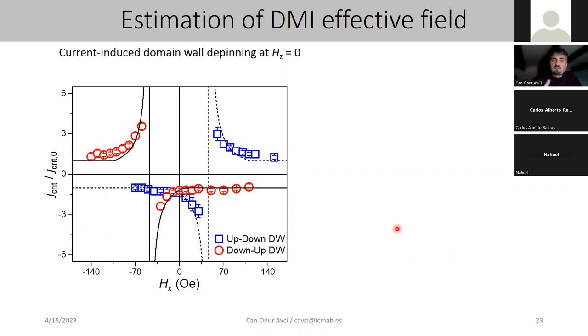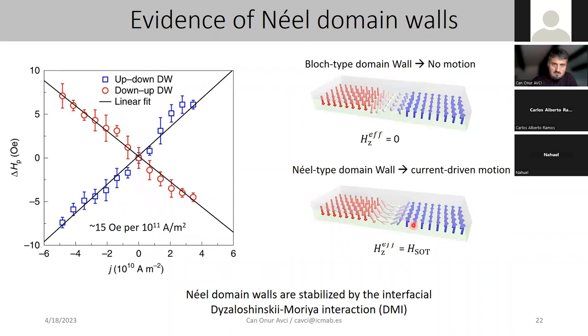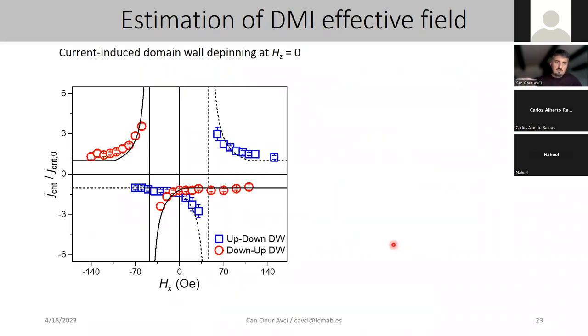the effective field that stabilizes these Néel type domain walls, by the way, these Néel type domain walls are driven by an effect called the Dzyaloshinskii-Moriya interaction, we can measure by doing the experiment in the presence of an in-plane field. Because as you can imagine, if it's a Néel type domain wall, then if you apply an in-plane field, you can rotate the internal spin orientation of the domain wall into a Bloch type and into an opposite Néel type.